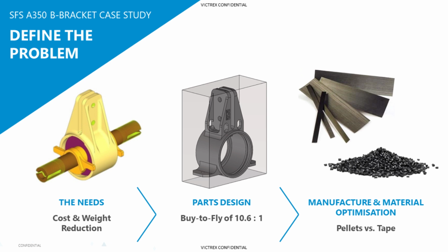So one of the big filters that we use is this buy-to-fly ratio. We look at the amount of material that is initially purchased, or is in that first billet that needs to go into the machine, in order to create the part that flies. By the pound, our materials that are heavily using carbon are relatively expensive, but when you look at the actual buy-to-fly ratio of a given candidate application, the real cost of that $3 a pound aluminum billet might be somewhere up near $35 a pound, based on a 10-plus buy-to-fly ratio, which is pretty typical for what we see.